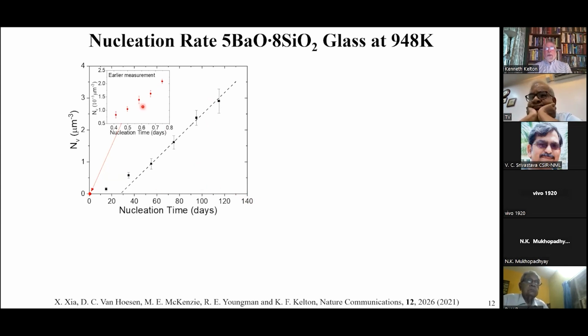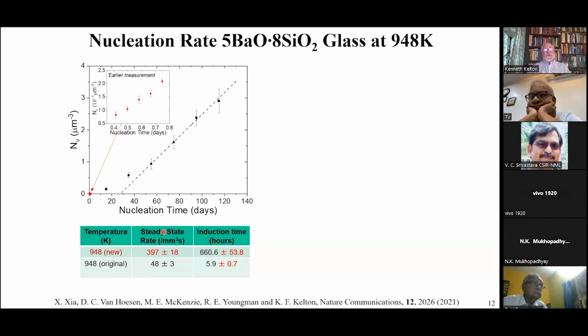These original data, which were argued to show the induction time and the steady state rates, really are only a tiny fraction of the whole relaxation behavior. And this is a problem with this method. Basically, these curves are self-similar, and so it's very difficult to tell when you finally reached true steady state. But if you take these new data, the steady state rate in the old data, these red data here, was 48 per millimeter cube second. The new data, the steady state rate is an order of magnitude larger than that. The induction time in the original data here was 5.9 hours. In these new data, it's a factor of 100 larger than that.